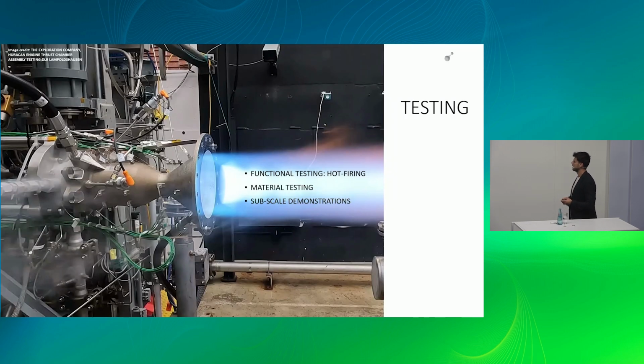About testing, the most crucial test is in the end the hot firing. So that happens after all manufacturing tests, and that is usually what qualifies the engine then. What you can see on the picture is the first generation of engine that we printed in 2022, I think. We did that with a partner, but material is the same, Inconel 718. So what happens here basically is you put your parts, so that's a combustion chamber, and on the left, injection head. You cannot really see it, it's frozen from the liquid oxygen.